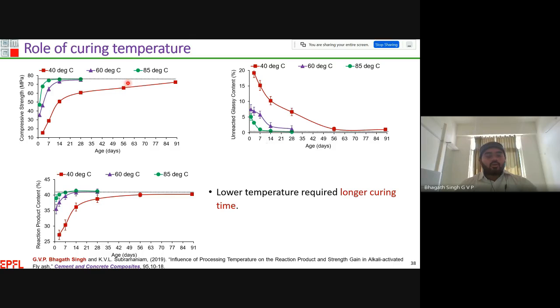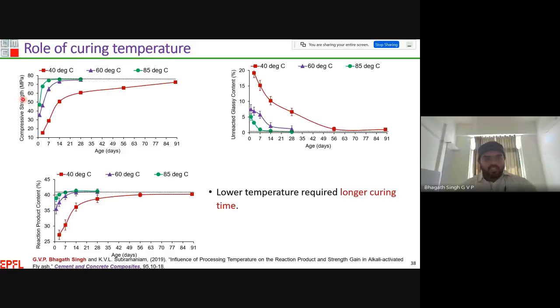And coming to the role of curing temperature, in the literature we used to use 60 degrees Celsius, 85 degrees Celsius, 105 degrees Celsius. Here the question is, is it really required to use such elevated temperatures? So I have used three different curing temperatures: 60, 85, as well as 40 degrees Celsius. As you can see in the compressive strength development, in the case of 85 degrees Celsius, I can achieve 100% compressive strength by 7 days. Thereby, there is not much improvement in the compressive strength afterwards.